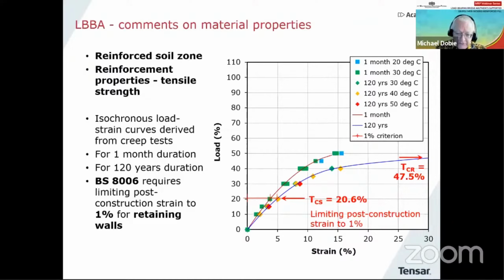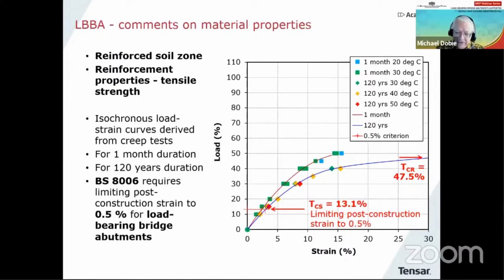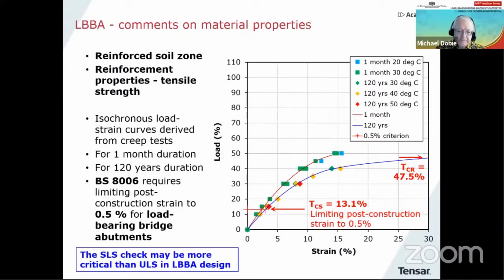Now that's to limit post-construction strain to 1% for retaining walls. But when it comes to load-bearing bridge abutments, the BS 8006 recommendation is that you limit post-construction strain to 0.5%. And so you can now see in this case, it's a lower value, it's 13.1% of the tensile strength. And when earlier on we saw that little window pop up with the 0.5% in it, that's what it was limiting when we set that within the design procedure.